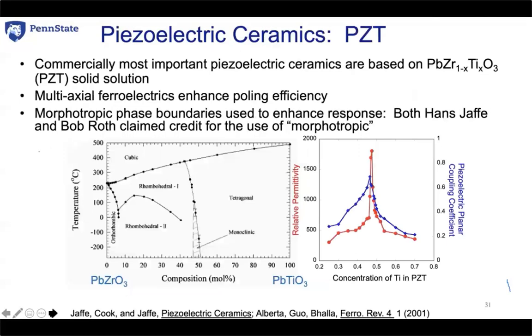We all know why we like lead zirconate titanate. It is commercially still the most important piezoelectric ceramic, and it's associated with this nearly temperature-independent boundary between rhombohedral and tetragonal distortions that leads to a range of transformation where we can get enhancements in the properties at a morphotropic boundary. Both Hans Jaffe and Bob Roth claimed that they were the ones who invented the word morphotropic. So they separately claimed that. I can't say which of them used it first or whether that was kind of a mutual discovery.